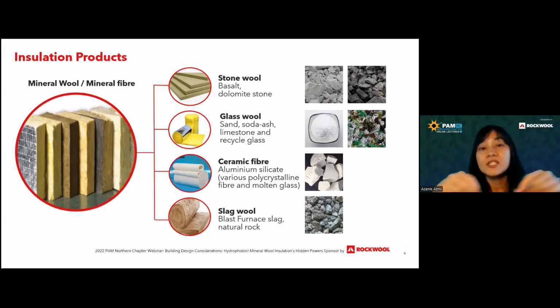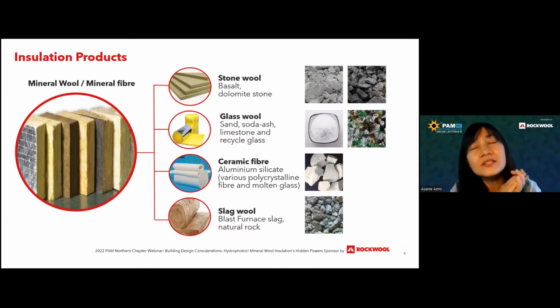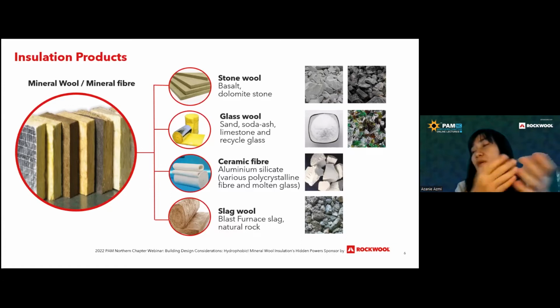Stone wool, as the name itself says, comes from basalt stones and dolomite stones. Glass wool comes from sand, limestone, and recycled glass. Ceramic fiber is also known as refractory material, mostly used for very high temperature applications in industry, where the maximum service temperature goes almost up to around 1,200 degrees C. It primarily consists of aluminum silicate, which includes fiber made from polycrystalline fiber as well as molten glass.